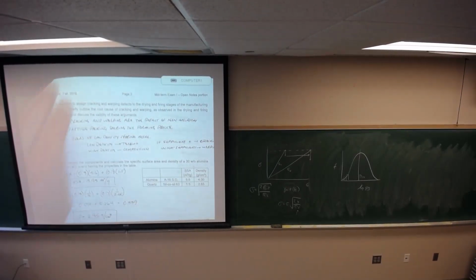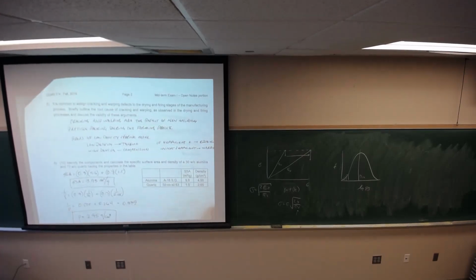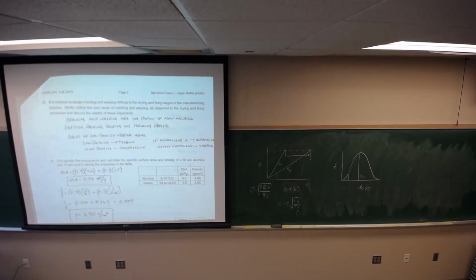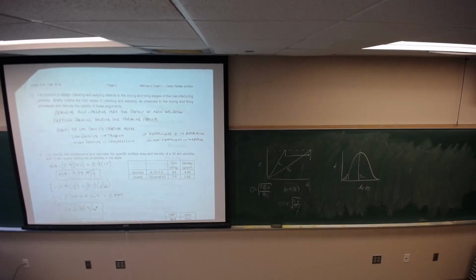And then this side here, the common cause of cracking in drying and firing stages in the manufacturing process. What's the root cause? Cracks are the result of non-uniform particle packing during the forming process. Low density shrinks more, you get some tension. High density and compression is sufficient strain, you get cracking. If not sufficient strain, you get warping.